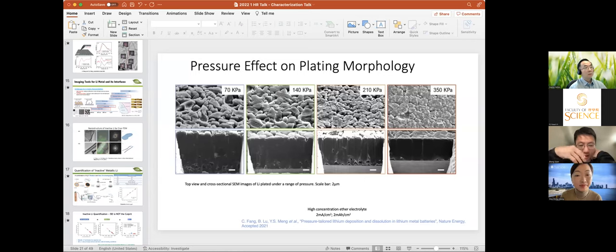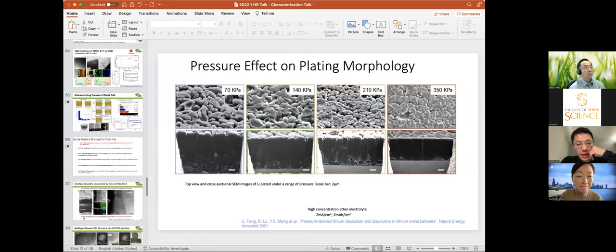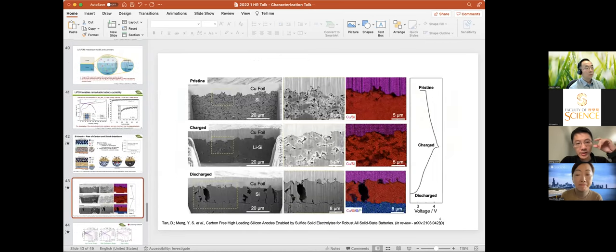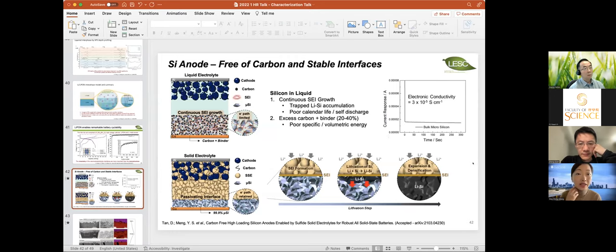I read your papers, the last page of the Science paper. You mentioned that you will be able to do a very high areal capacity and the silicon is quite thick. Since you use such a high amount of silicon, how do you tackle this? Is there any electrical conductivity issue while you are doing charge discharge? Yeah, thank you, Zijian. So the silicon is carefully chosen. We found a vendor in the field who can produce micron silicon with reasonable conductivity. You can see this conductivity measurement here on the slide. So it's important to double check the conductivity of your silicon. It needs to have the nature of a mixed conductor, right?